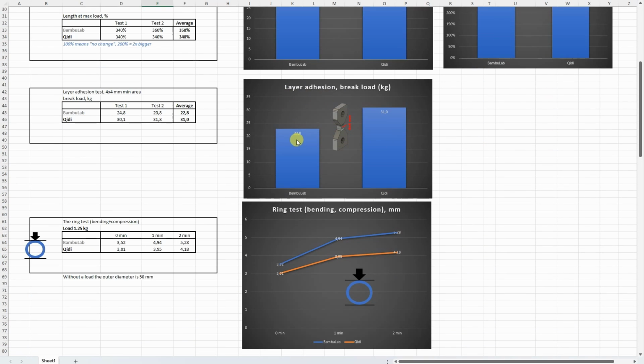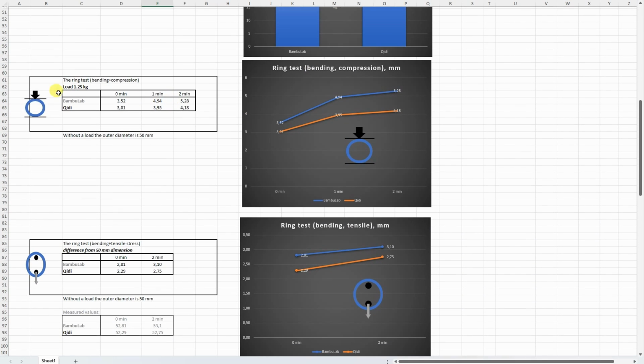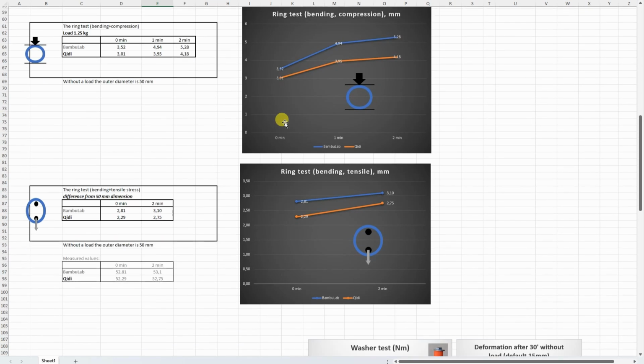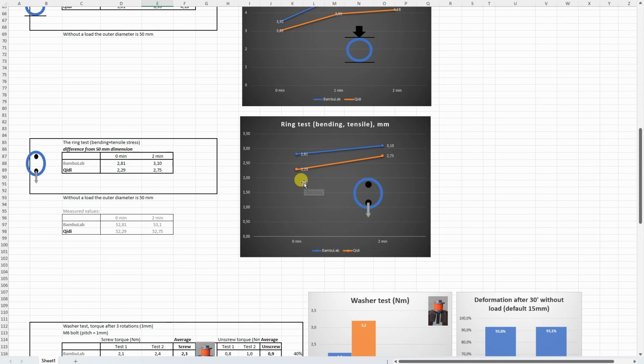Now on layer adhesion, here we can see some bigger difference, 31 kilograms. This is really good, not only for TPU filaments, but also it was good to see in both cases some prolongation before the break. And this is that ring test with the compression, and here smaller values mean less deformation, but it doesn't mean that this is better, it depends what you need. So maybe if you need more elasticity, this is better for you. And similar results with less deformation on Qidi filament.